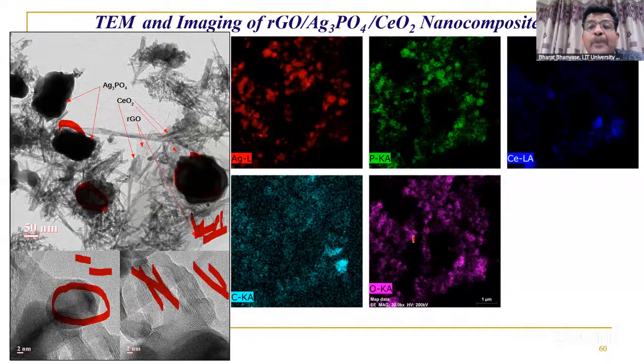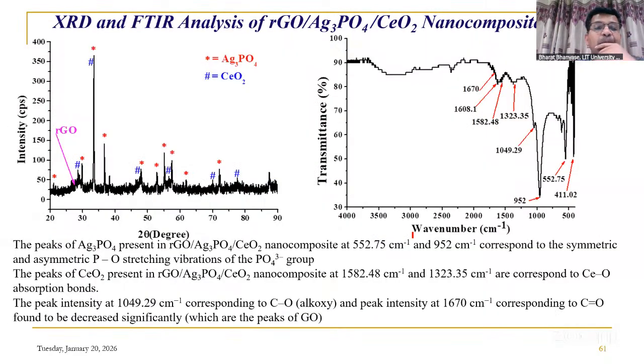So you can observe this is a well dispersed material prepared by ultrasound, which is confirmed from XRD analysis also. We can observe the peaks of cerium oxide as well as Ag3PO4, and the peak around 25 degrees 2-theta confirms the formation of rGO.